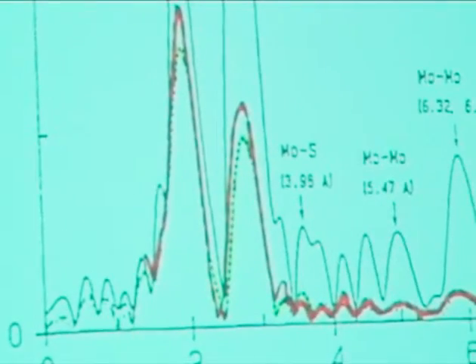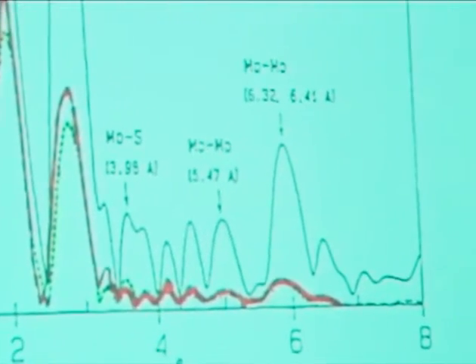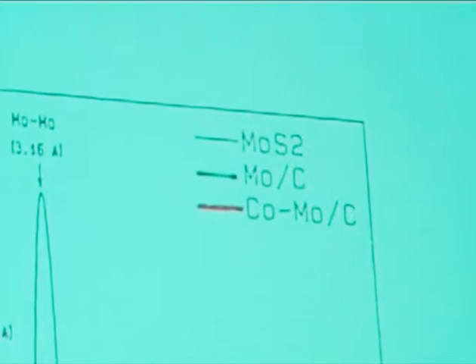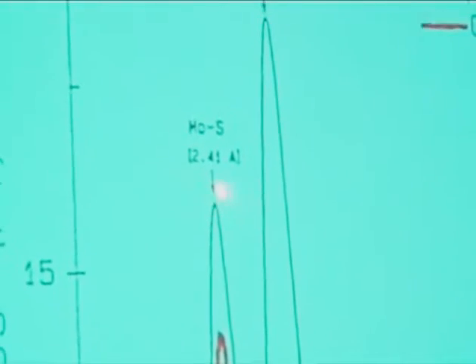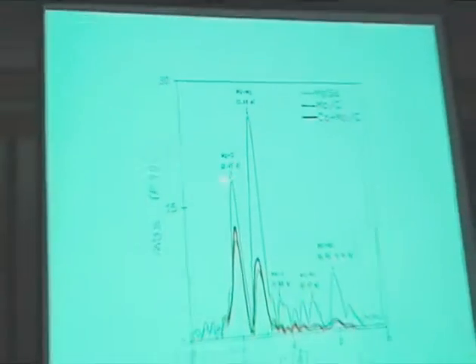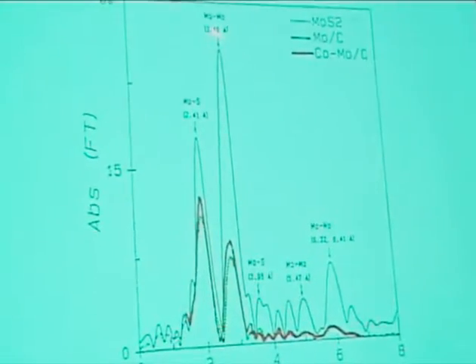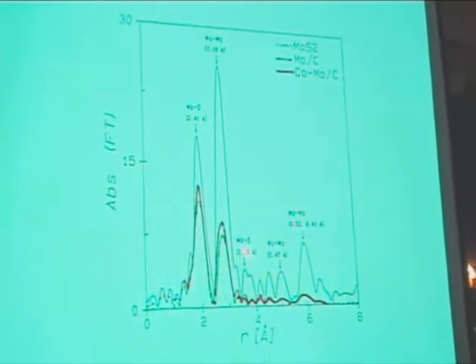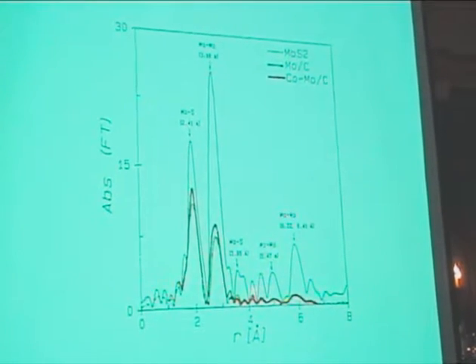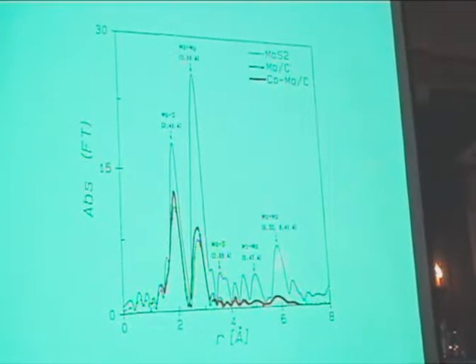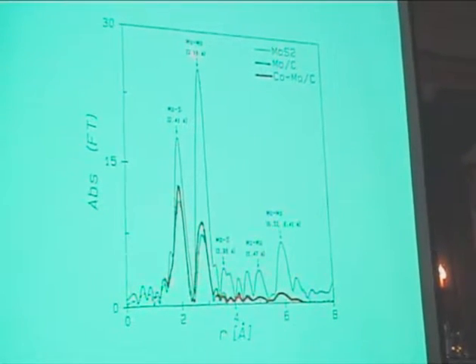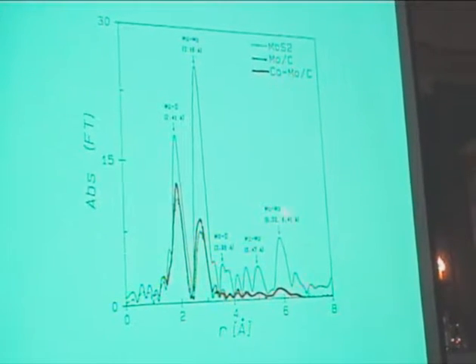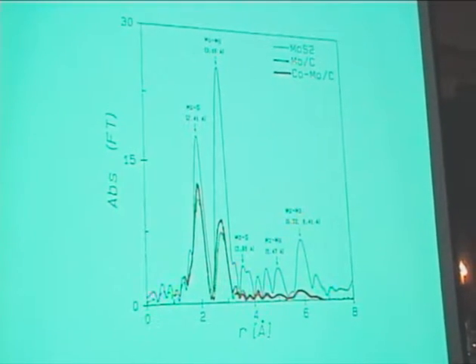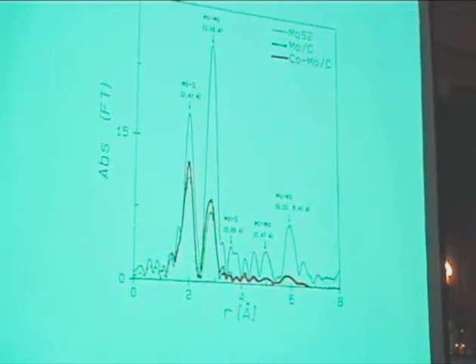And here I'll show you the EXAFS spectrum, Fourier transform, so we see the peaks at certain distances. And in black you have the molybdenite, which is a single crystal. So you see a peak for the molybdenum, and it's molybdenum EXAFS, so at 2.41 angstroms, you see a sulfur neighbor. At 3.16 you see a molybdenum neighbor. Then 3.95 sulfur, and here is another molybdenum. This is exactly double the distance of this, because this atom, molybdenum, is right behind this atom. So it's molybdenum, molybdenum, molybdenum in a linear fashion.